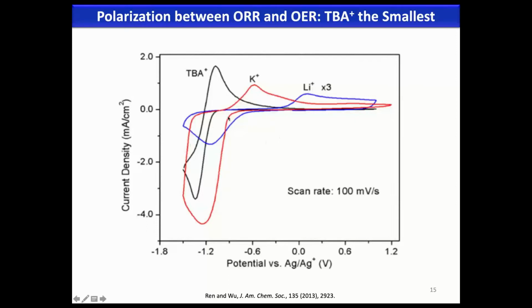Combining with a soft acid, look at that, the polarization is much smaller. And if you go for an even softer cation, tetrabutyl ammonium, which is much bigger, the polarization is even smaller. I just want to highlight this interesting phenomenon from this paper: you choose different charge carriers, you have the same oxygen reduction and the same oxygen evolution, but the entire kinetic behavior can be completely different.